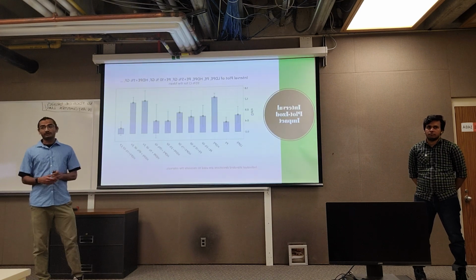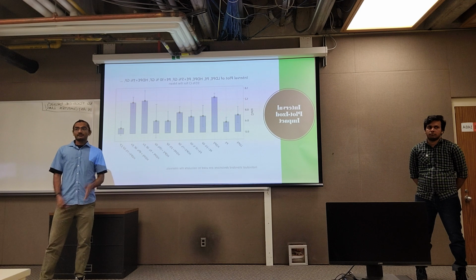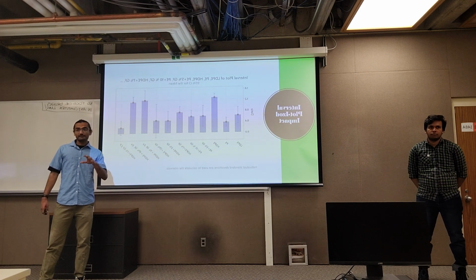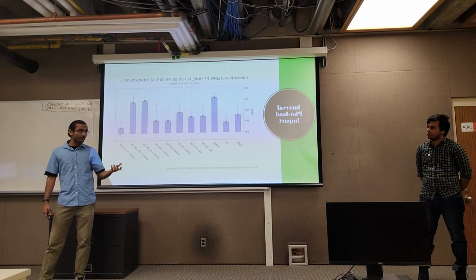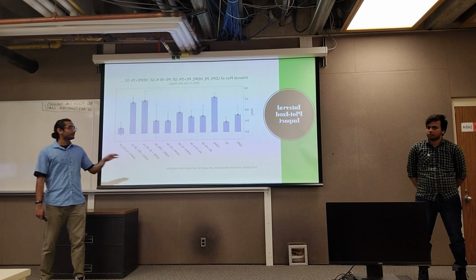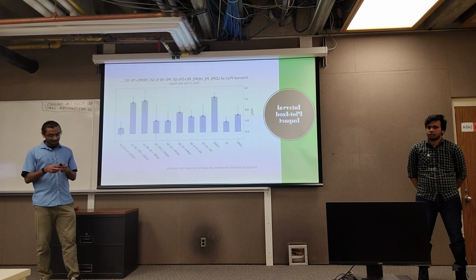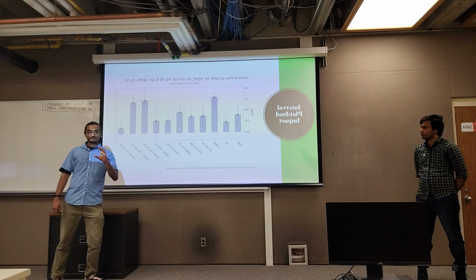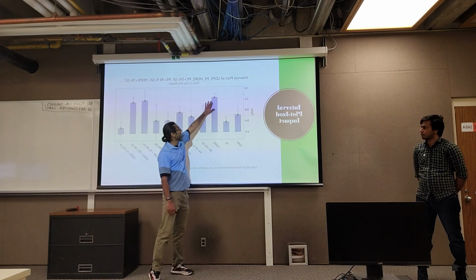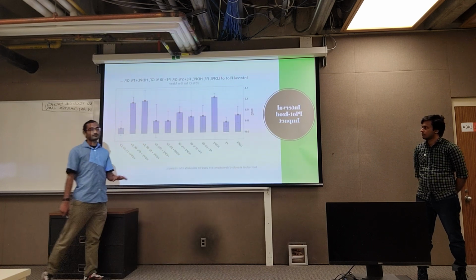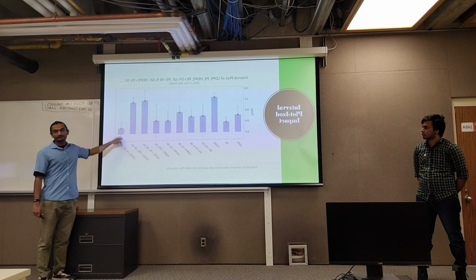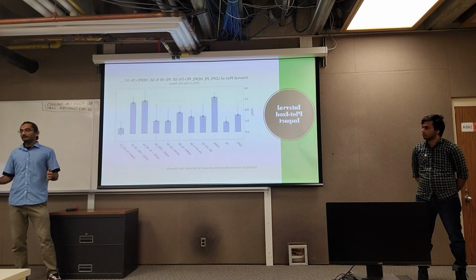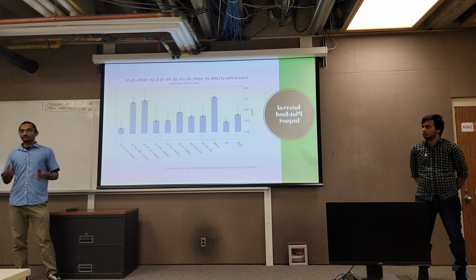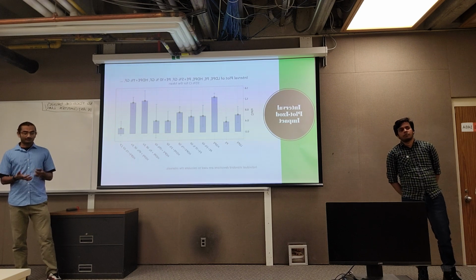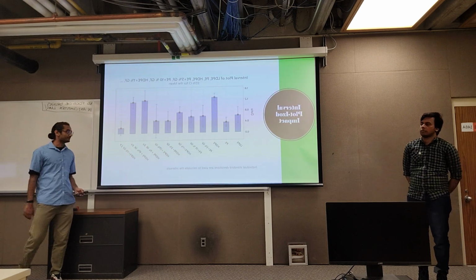The different part was that by making the samples using the coupling agent, there was a high decrement in the impact test results. As you can see, with HDPE and the use of the coupling agent, there was a subsequent decrease, which showed that the coupling agent was not able to bind the matrix and the reinforcement.